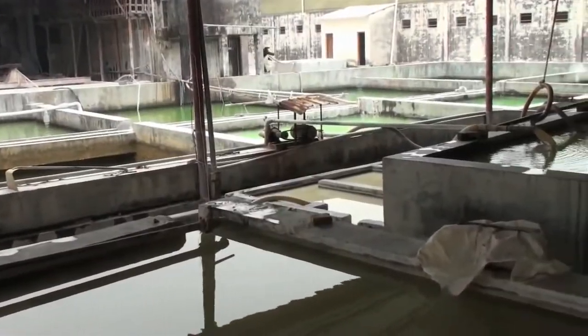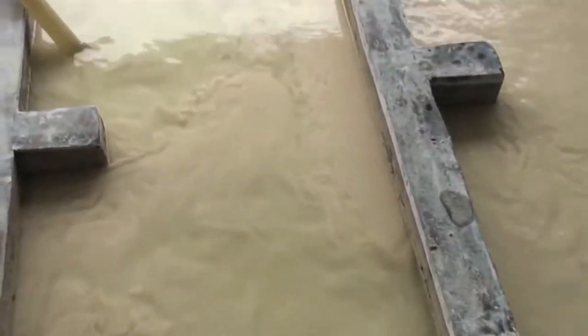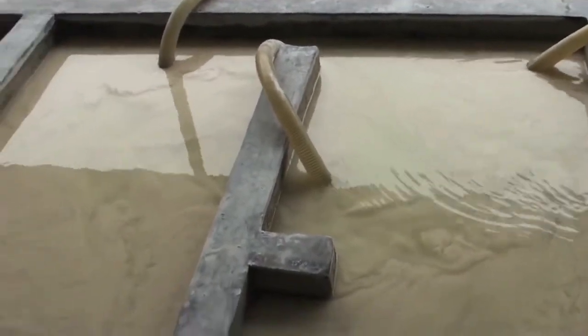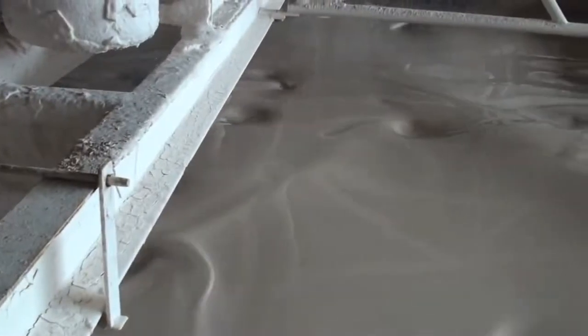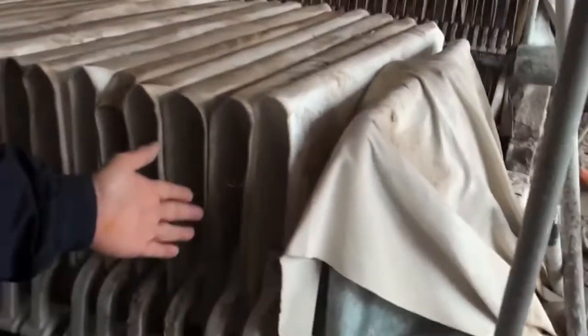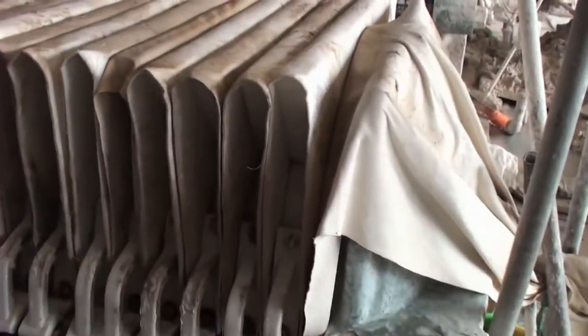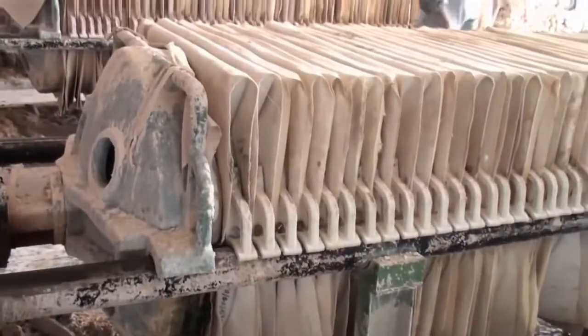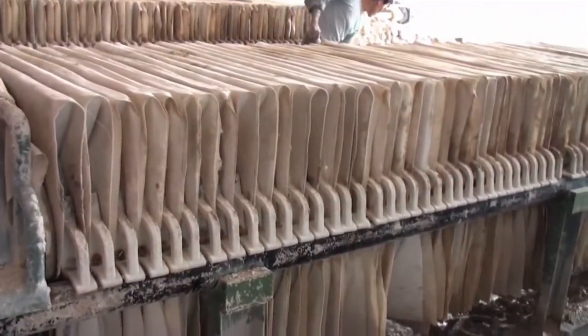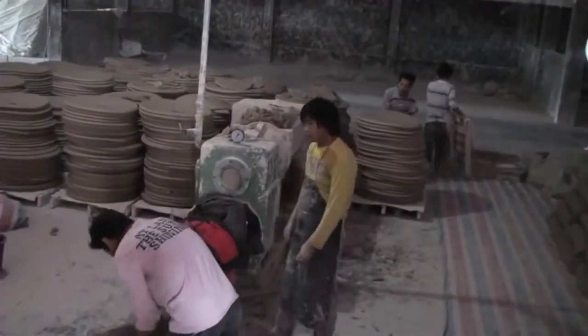The powder is then mixed with water and travels through a complex maze of channels where the larger, heavier pieces that can't be used to make clay sink to the bottom, while the finer, more pure particles remain suspended in a thick slurry. At last, our raw materials begin to look like clay. To remove the excess water, workers press the clay into large wafers which hang in racks as the water drips away. Ultimately, the wafers will be compressed down into carefully weighed and measured logs.